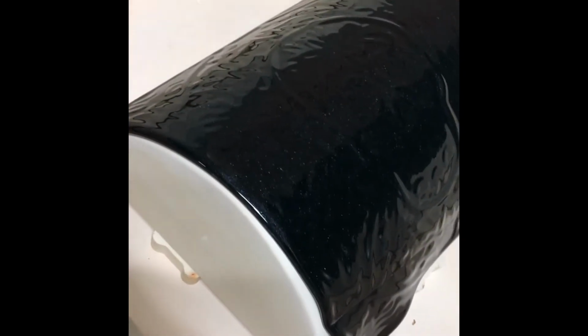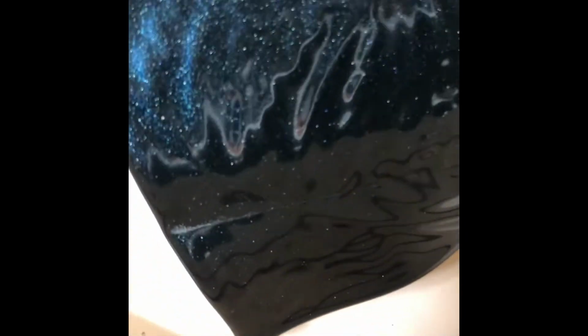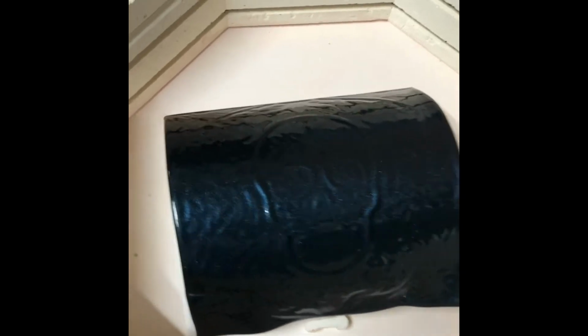So there you go. Okay, so I've opened up the kiln and it worked. The angle gave me what I needed to get that piece to fold down. There's obviously a crease in it yet, but that's okay because I'm going to flatten this out in a full fuse next. This didn't fully lay down. There's a little bit of a gap. That's okay too. Look how close I got to touching that thermocouple, so I got lucky there, I guess. So it's all right that it didn't fully lay down because I'm going to fuse this thing flat next, but I just want to share with you that this worked.